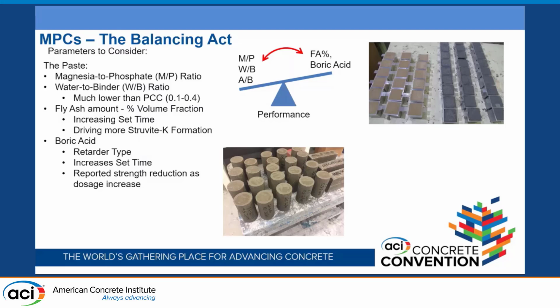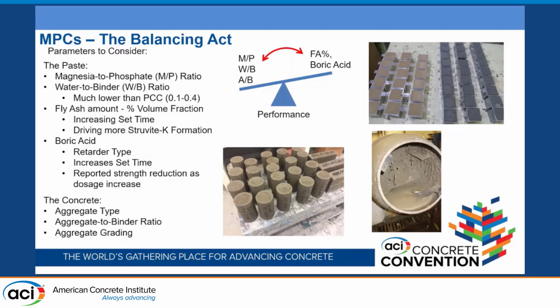Most people are around a 0.2. Fly ash amount, you're upwards of 40, 50, 60% fly ash. You want a Class C, Class F. You typically want a Class C in these. Class C can help you drive the formation of more struvite. And then boric acid was our retarder type, increased set time, but then also that strength reduction that I showed on the last page. And then it's the whole balancing act between all those.